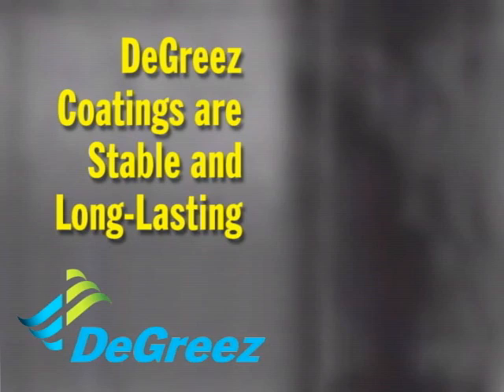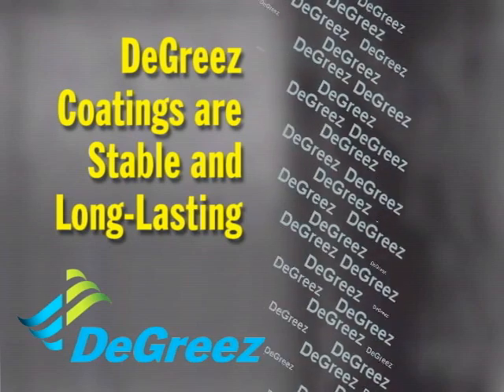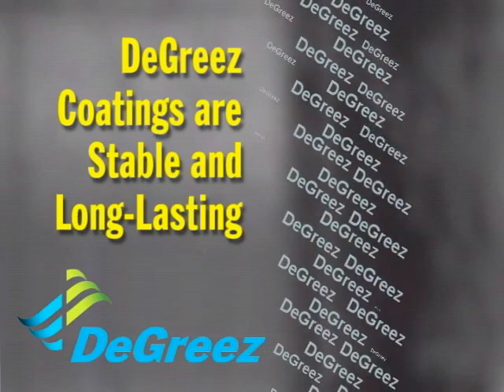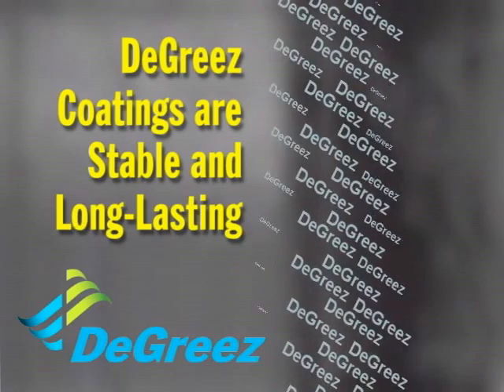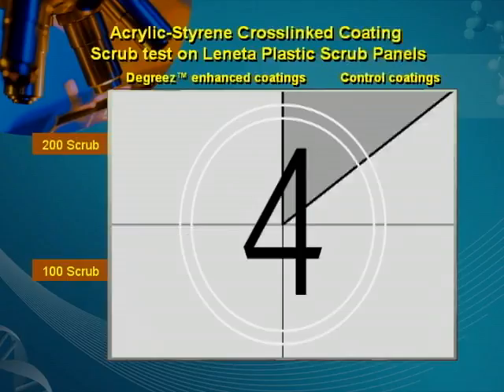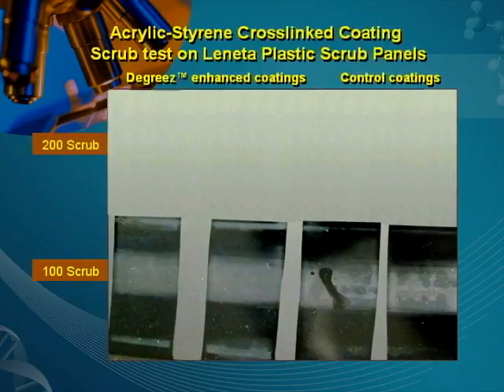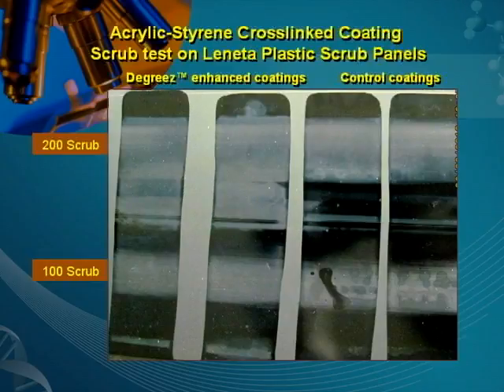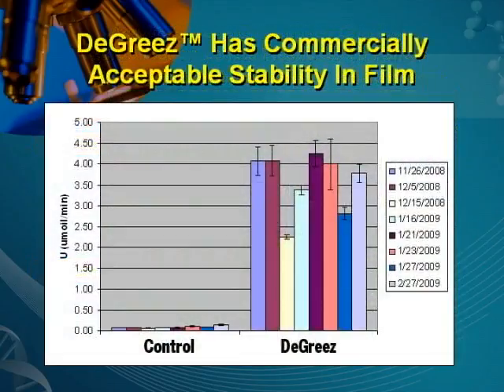And this self-degreasing functionality is catalytic, meaning that it continues to repeatedly degrease the surface over and over again. Catalytic coatings built by Reactive Surfaces have been shown to remain functional for years. Significant amounts of physical testing back up the product line offering. When enzymatic activity retention analysis is conducted after standard coating scrub testing, significant activity remains even after 200 scrub cycles. DeGreez exhibits long-term stability in cast films.